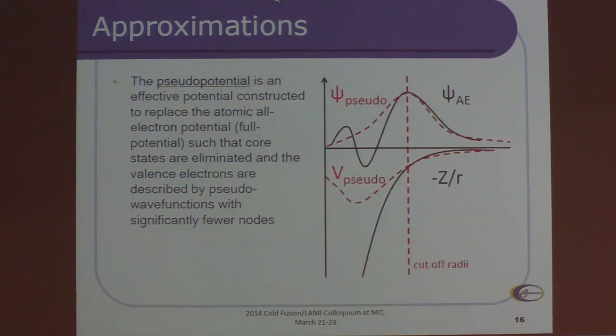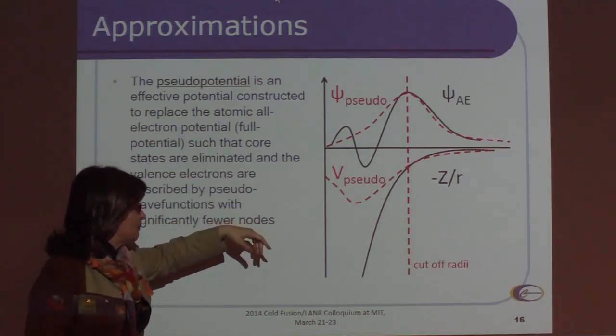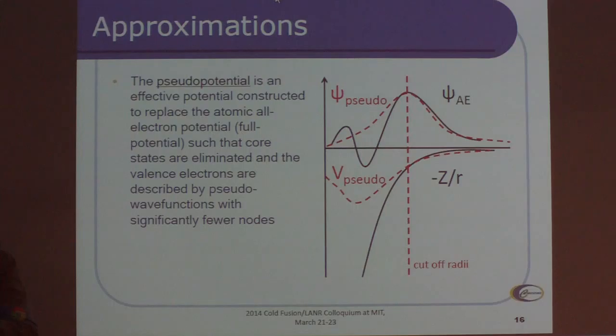And if you ever get involved with the DFT codes, then there's one more thing you probably will encounter, and that is pseudopotentials. What are those? I already mentioned palladium, 46 electrons. Do we really need to account for each of those electrons to solve the problem? Most of them, well, exactly 36, sit very close to the core. And they don't really want to even interact with anything else. So only valence electrons, that's what's important, and that's what we want to account for.